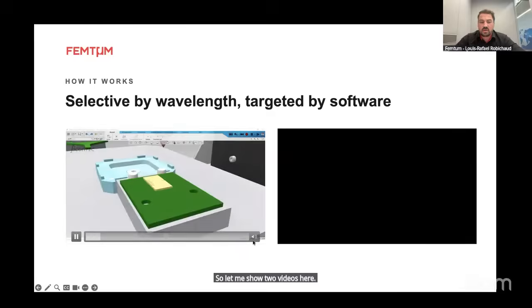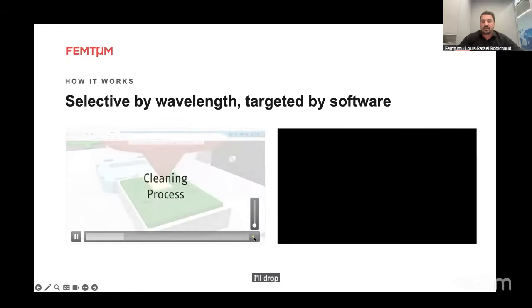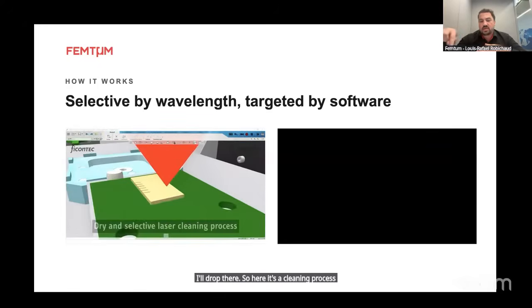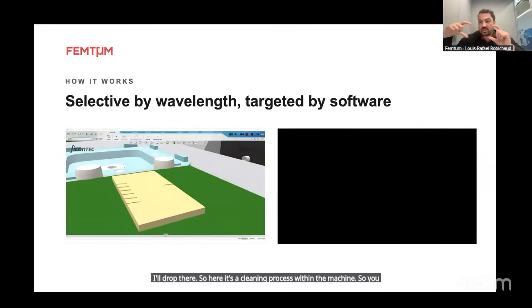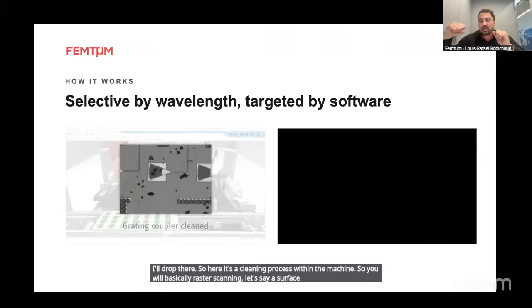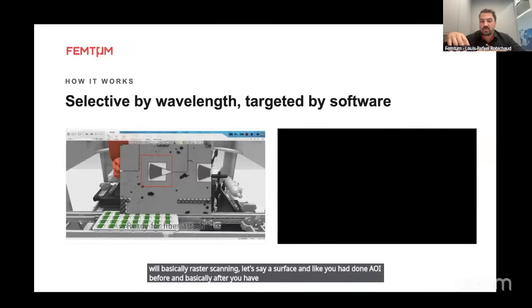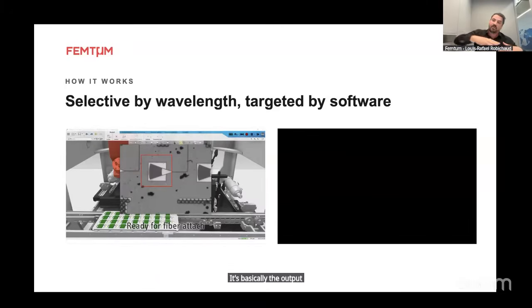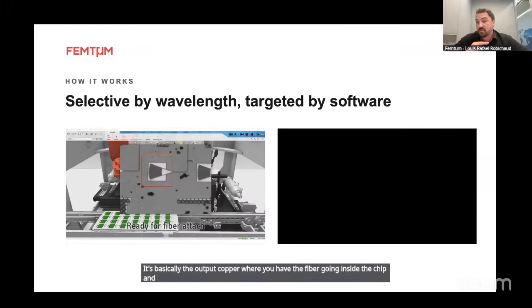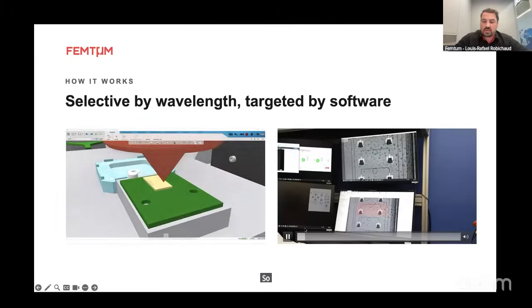So here is a cleaning process within the machine. You're basically raster scanning a surface, and you have done AOI before, and after that you have a very selective laser ablation. This is what we're looking at, the grating coupler. It's basically the output coupler where you have the fiber going into the chip, and that surface needs to be pristine clean because otherwise you would just burn the die. Let me show a second video.